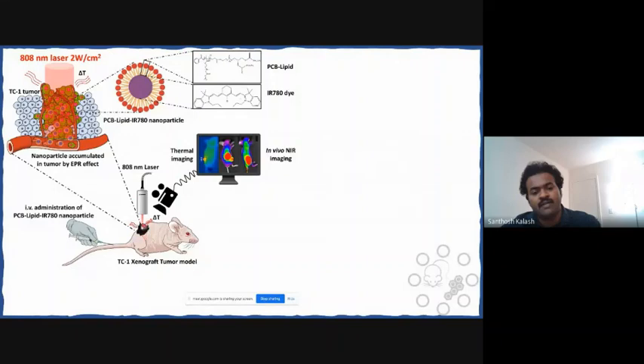We developed this tumor model by injecting the cancer cells subcutaneously. Once the size of the tumor reached 100 mm³, we started the therapy. We injected the nanoparticles intravenously, and then checked at what time point they have a high accumulation in the tumor. Once we fixed that time point, we did the laser irradiation. We used an 808 nm laser, and the preclinically approved power is 2 W/cm². After irradiation, we also checked the superficial temperature using a thermal camera, to see whether they reached the ablation temperature or not.